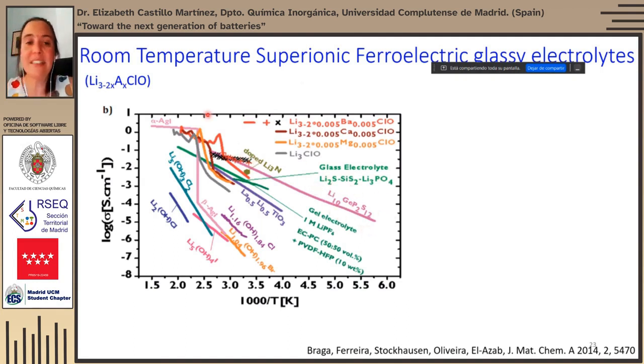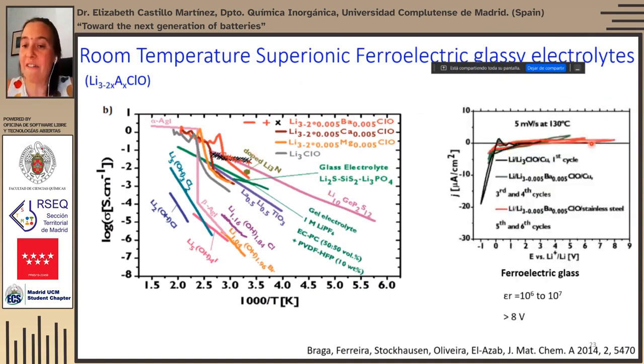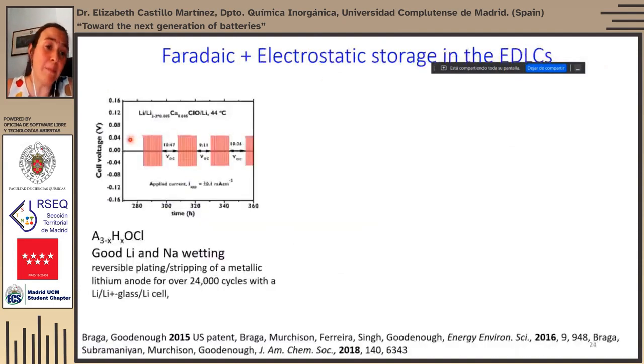And in some sense, these materials are not as sensitive as sulfides, although they have to be treated with some care as well. This type of glass electrolyte additionally has a very large voltage stability window, in excess of 8 volts. You can see they don't decompose at 8 volts above lithium ion. And what is very important, they have very good wetting properties towards lithium, and they enable the reversible plating and stripping of lithium metal. Actually, they can be plated and stripped for more than 24,000 cycles in a lithium glass cell.